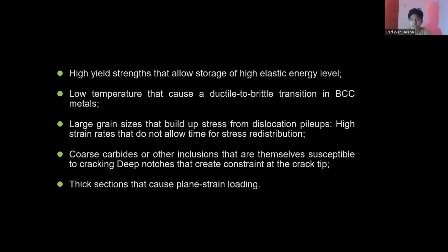High yield strength that allows storage of high elastic energy levels, low temperature that causes a ductile to brittle transition in BCC metals, large grain size that builds up stress from dislocation pile-ups, high strain rates that do not allow time for stress redistribution, coarse carbides or other inclusions that are themselves susceptible to cracking, notches that create constraint at the crack tip, thick sections and plane strain loading.